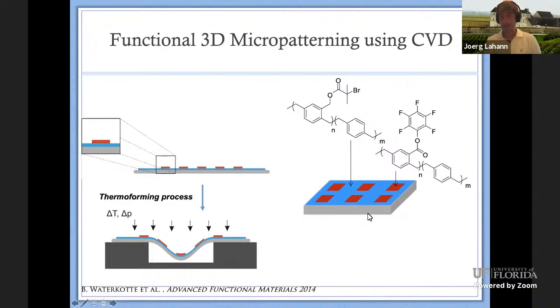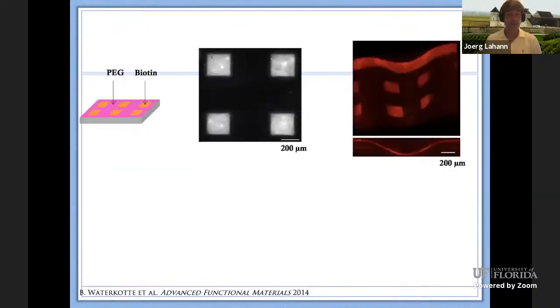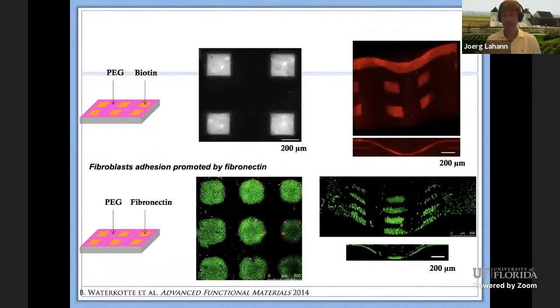So the backbone is protein resistant, so cells don't like to stick to that. And then here we immobilize through this activated ester group. We immobilize adhesion molecules to then guide cells into those patches. And then in conjunction with the thermoforming, we can create well structures that really allow us not only to place cells in there, but also then locally pattern within those well structures, which is something that is really difficult to do otherwise. So here's the confirmation of those data, and you see the cells are actually really following those patterns as well here on the bottom.